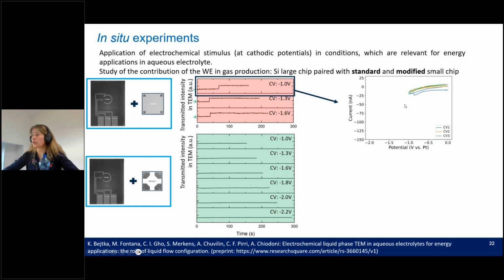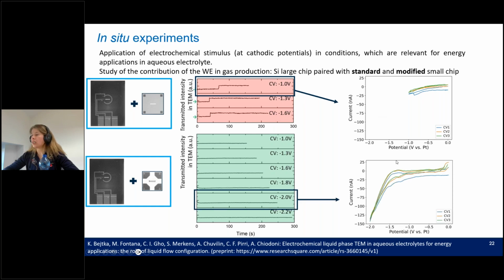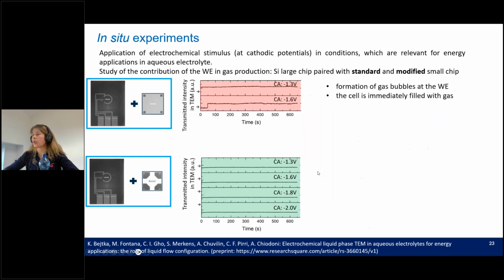So this is the situation, the CV in the standard configuration, and here I show the CV acquired in the potential range between 0 and minus 2 volts versus platinum, and we can see that we actually obtain nice predictable cyclic voltammetry curves. And when we perform the chronoamperometry, we observe similar behavior.